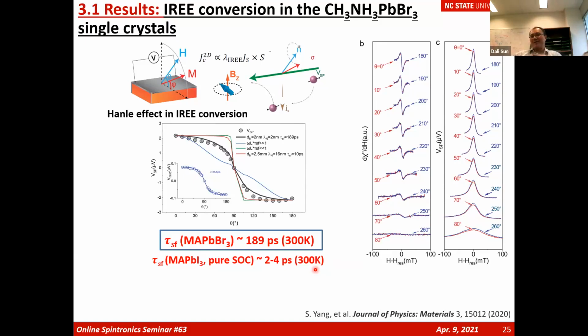189 picoseconds. Just a reminder, if it were caused by pure spin-orbit coupling, people measure from pump-probe measurements at room temperature only 4 picoseconds because of the lead. MAPbBr3 contains the same heavy metal, lead, yet exhibits a larger spin relaxation time, which is not expected. So that can also be contributed by the formation of the Rashba effect through the Dyakonov-Perel mechanism, because mobility is low, but the spin relaxation time is inversely proportional. So that gives you a higher spin relaxation time due to the DP mode in the 2D electron gas.